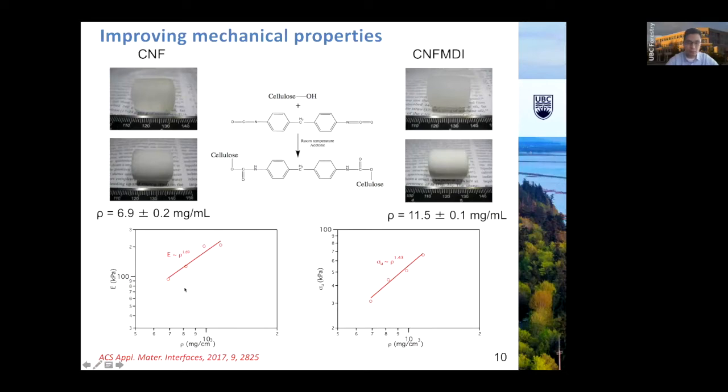Then we look at the mechanical properties. I show here the mechanical property increases non-linearly with the density, meaning the elastic modulus, Young's modulus, as well as the compression stress. It all increases with the power law equation, meaning we can make a lightweight material that is also super strong. This is by some simple modification after forming the hydrogel.